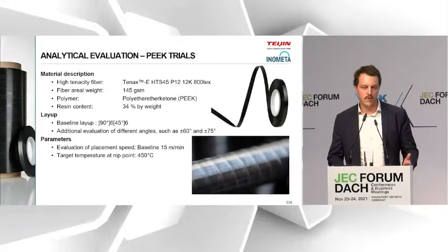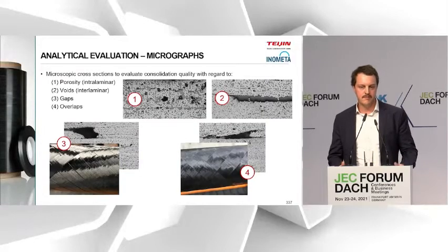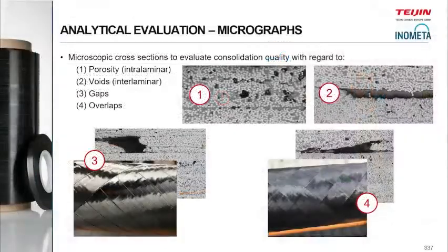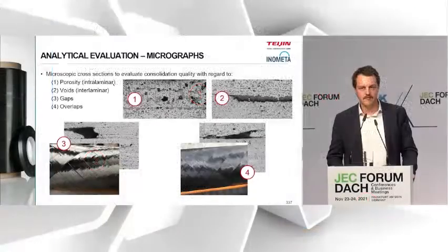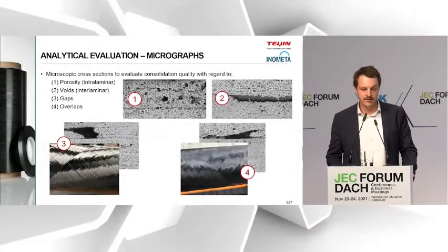First, an example of what we do not want to see in the tape. With the quick cross sections we perform, we can easily get quick feedback on some defects we clearly do not want to see in the material, such as porosity or voids between different layers, and as well, if you look below, gaps or overlaps, which then result as well in voids in the material, which clearly decrease the mechanical performance of the final application.